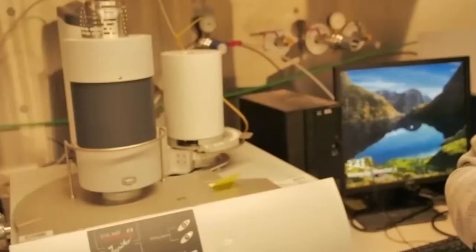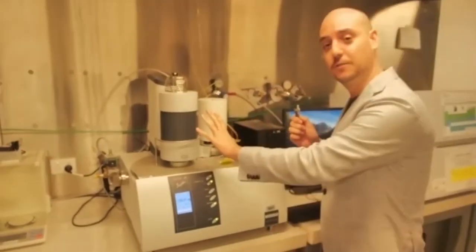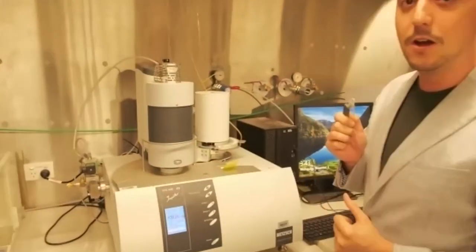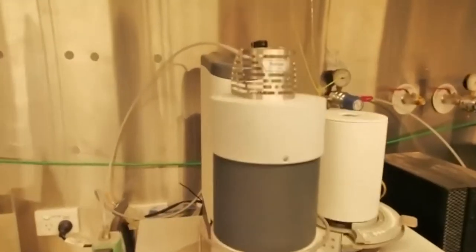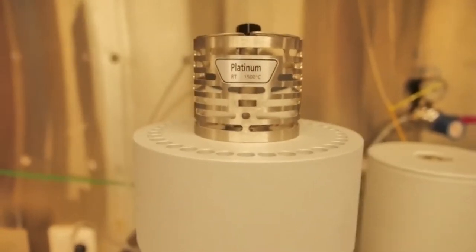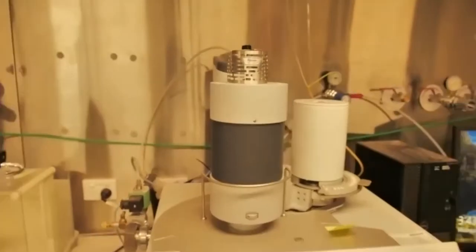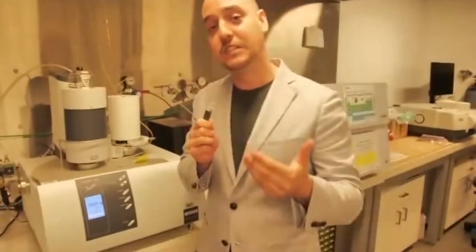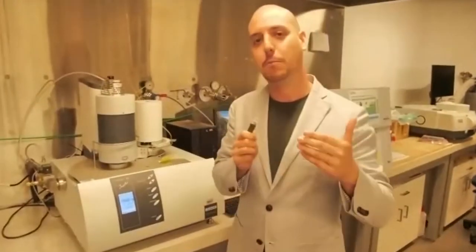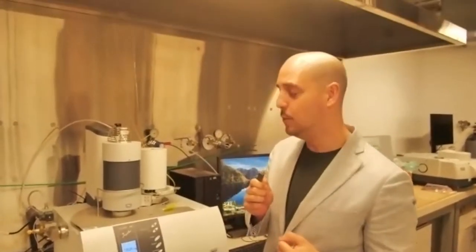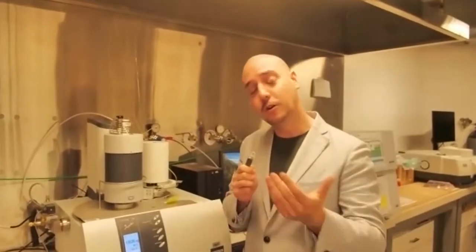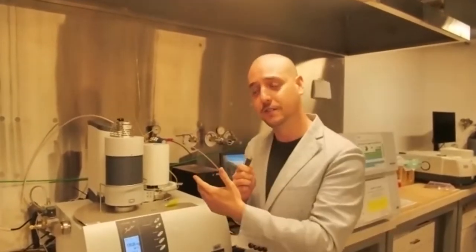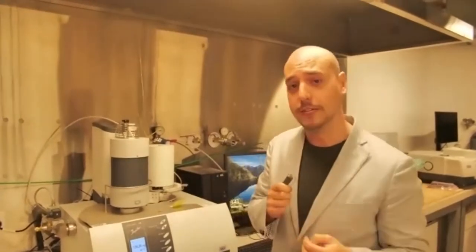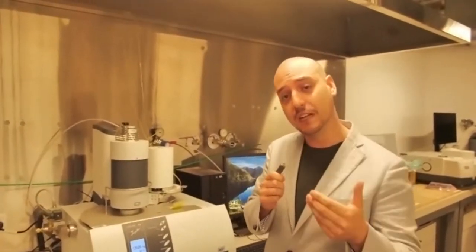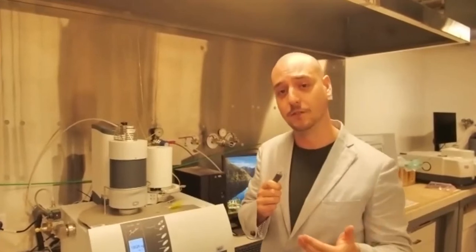Now we take that sample and we insert it in a furnace. This thing here is a furnace that can go up to 1500 Celsius. Now, what do we do in this furnace? We can control the temperature that the sample is exposed to, and we can measure the mass, so we can see how the thermal decomposition takes place. We can also control the oxygen environment within the furnace so that we can induce oxidation reactions, which are quite important in the process of fire development.